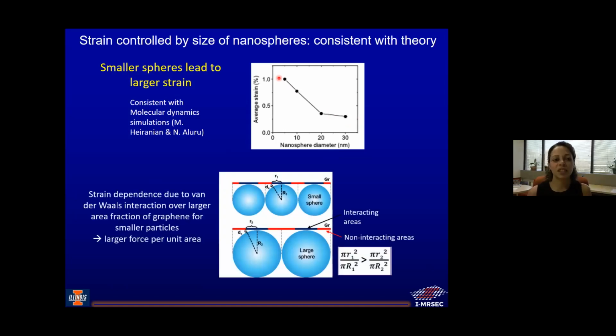And the physical reason for this is actually relatively straightforward. It's basically that, I'll just show you without looking at the numbers, if you look at the image here of small spheres, you can see that there's a lot of graphene in contact with the smaller nanospheres. So there's a lot of strained graphene. If you look at the larger spheres, the relative area of strain to graphene is smaller. Okay, so for the small spheres, you have a larger relative area of interacting and strained graphene than you have for the large spheres, right? That means for the small spheres, you get more average strain than you do for the large spheres. And that's exactly what we saw.